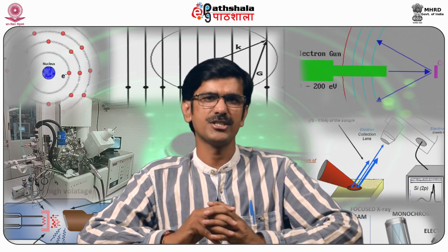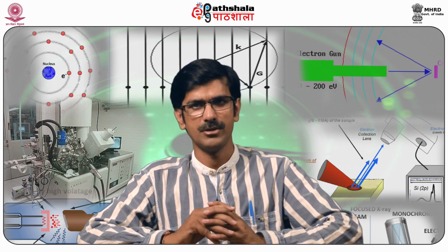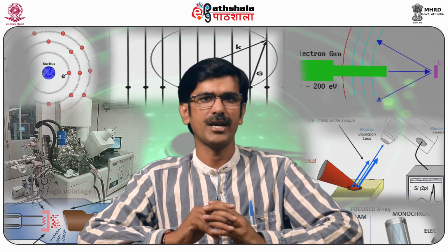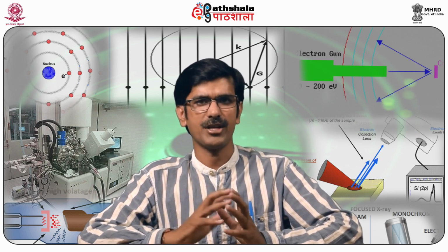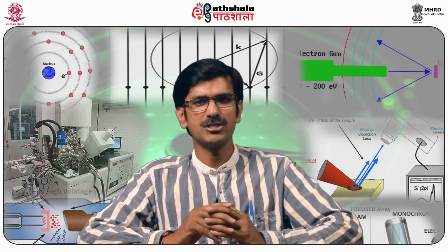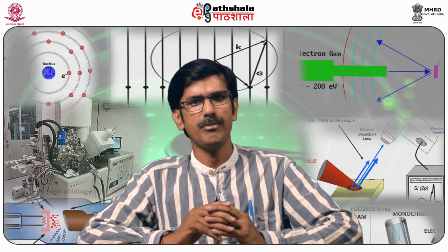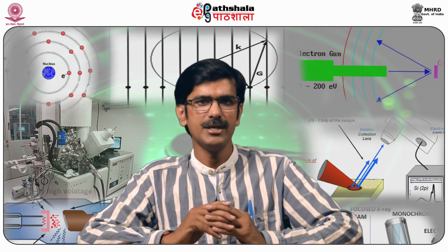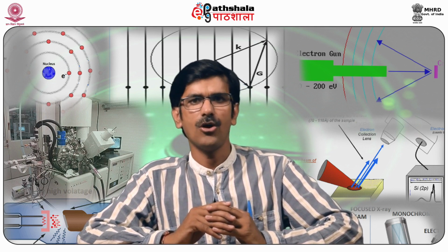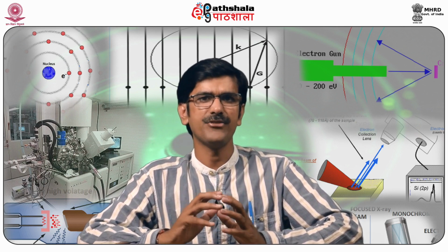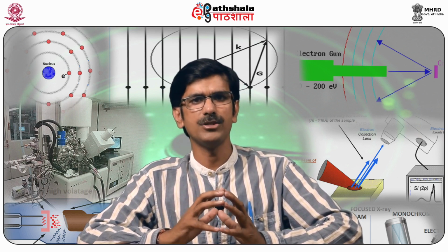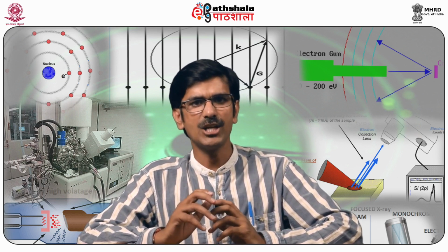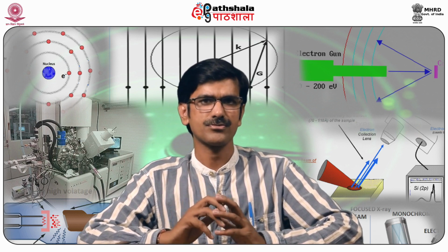The origin of hysteresis is ascribed to 2 factors. One is the thermodynamic factor and the other one is pore connectivity or the network effect. The thermodynamic stability is associated with the metastability of adsorption or desorption branches. Namely, the capillary condensation or evaporation may take place at a different pressure as compared to the pressure of coexistence between the gas and liquid-like phase in the pores.